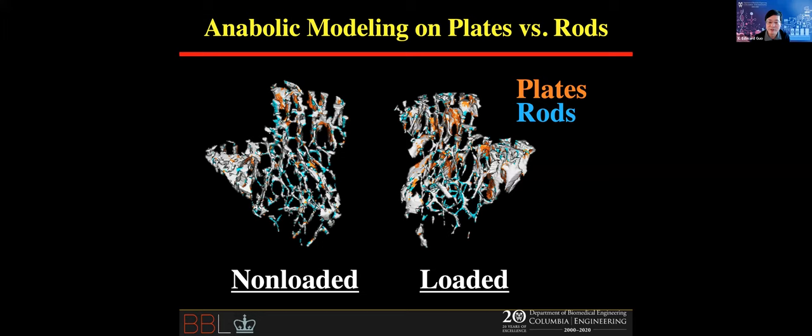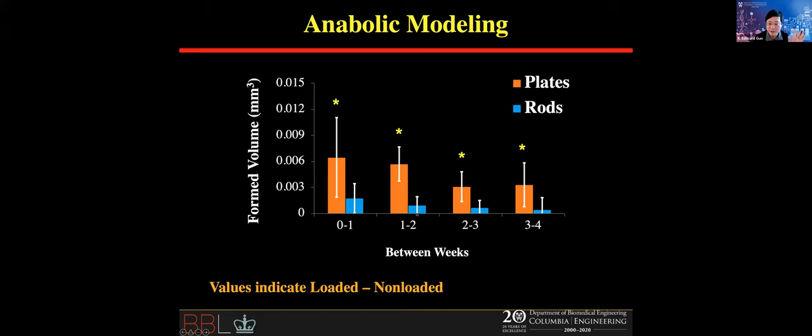Left side is unloaded, right side is loaded. So definitely, you have more patches going on in color, right? In the blue and in the yellow, that means new bone formation. You can see that you have much more yellow in the loaded one and some in the blue. If we quantify them, indeed, in the anabolic modeling, 1st week, 2nd week, 3rd week, and 4th week,